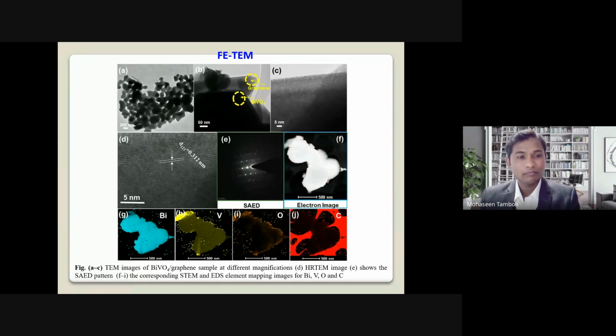So you can see figure D. It shows that the lattice fringes match very well with the bismuth vanadate structure, and figure E is the SAED pattern. Figure F is the electron image. You can see figures G to I, which show all the elements: bismuth, vanadium, oxygen, and carbon. In the case of XRD, we observed no carbon peak, but when we check with elemental mapping, the carbon is present here.